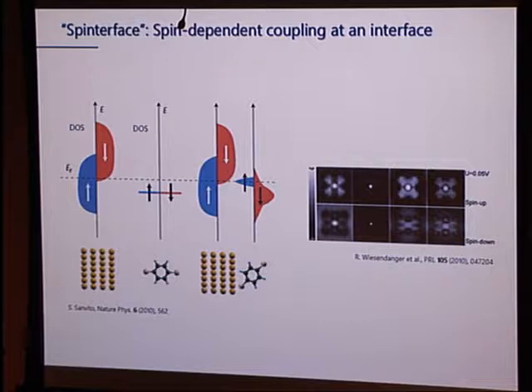And if that happens, then it might just be that I get a high density of states of one spin that sits right near the Fermi energy, and that density of states is then responsible for filtering spin in and out of the active material. There was then some evidence by Wiesendanger and co. with spin-resolved STM that did show that spin up and spin down for this molecule, whatever that may be, on the surface does look different, saying that there is indeed a spin-dependent interaction with the surface.